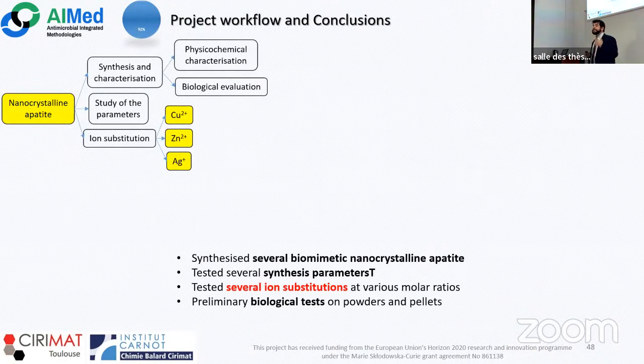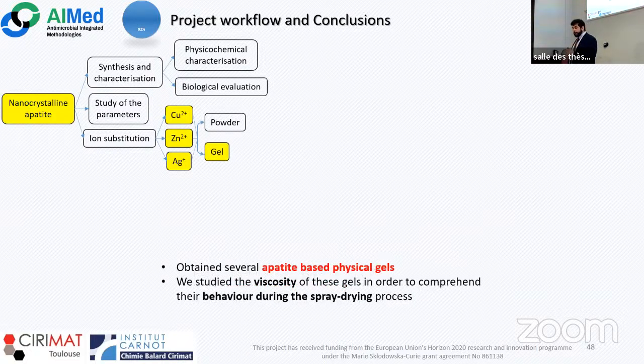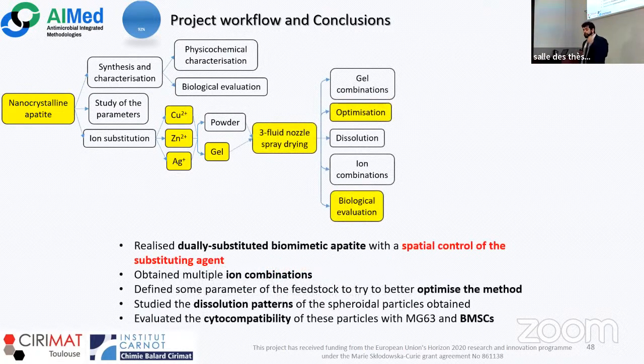So, in conclusion, we started from our nanocrystalline apatite, and we managed to synthesize several biomimetic nanocrystalline apatites. We tested several synthesis parameters and several ion substitutions, and also made some biological tests on the powders and on the pellets. We also managed to prepare several physical gels and to study their behavior in view of the spray drying process. And with the spray drying, we managed to realize many particles with a spatial control of the substituting agent. We obtained several ion combinations, and we defined several parameters to try to optimize the method at best. We also studied the dissolution patterns and the cytocompatibility of these particles.